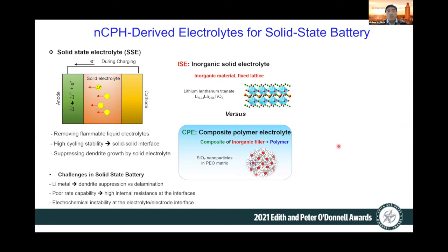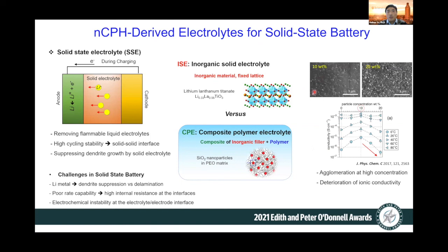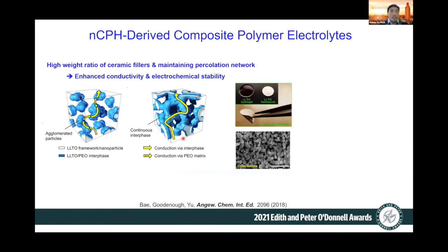But they have a significant challenge, because when you want to combine this inorganic filler with the polymer at a higher concentration, often you cannot monotonically increase the ionic conductivity. Within a certain range, you will start to see a plateau of ionic conductivity. This actually results from the aggregation of these inorganic fillers. That will lead to deterioration of ionic conductivity, even with more ceramic filler. So we try to explore the structural advantage of these interconnected, highly porous conducting polymer hydrogels as a template.